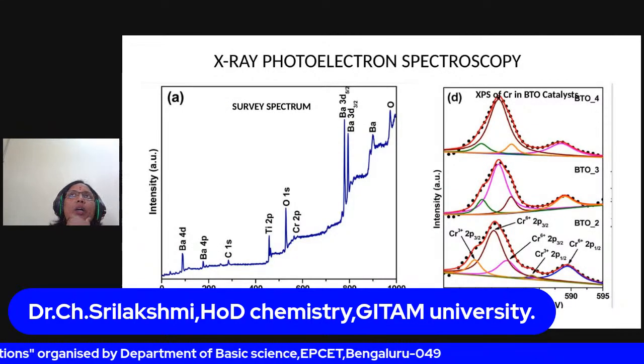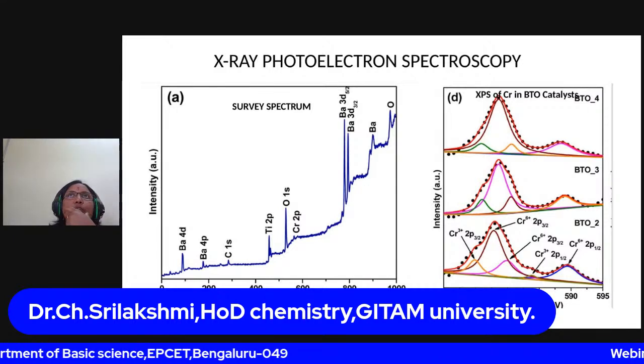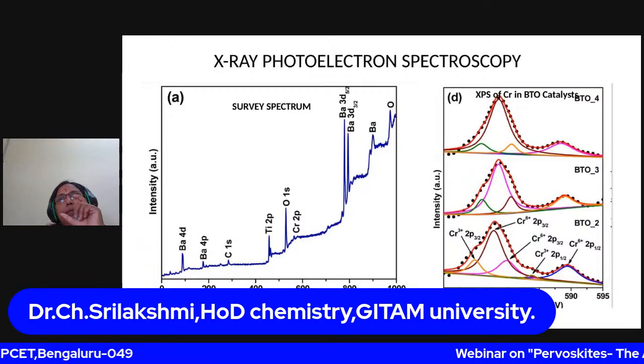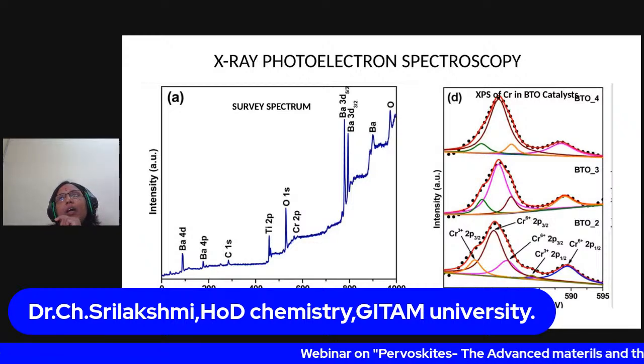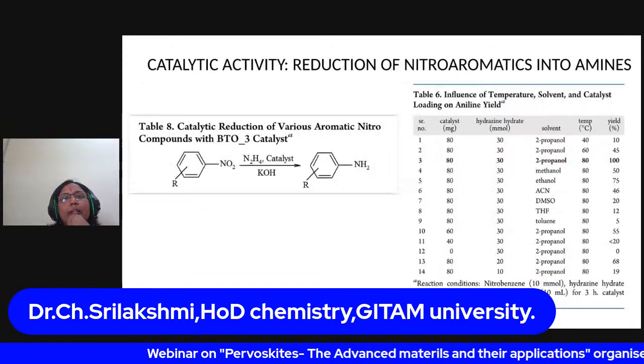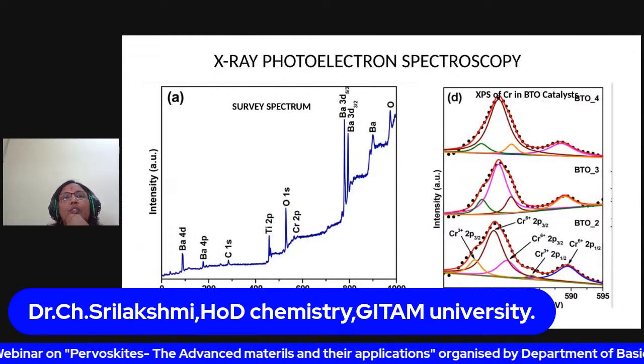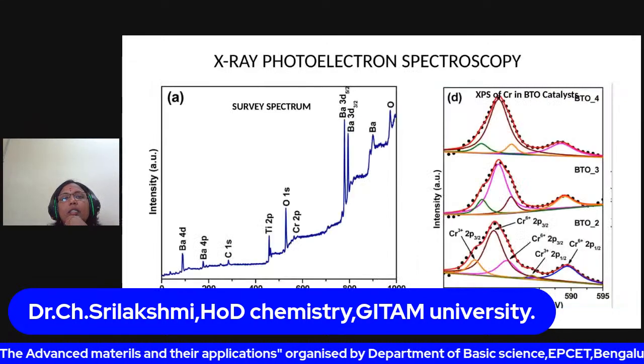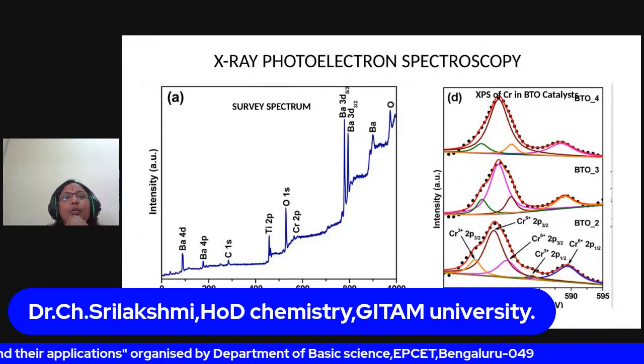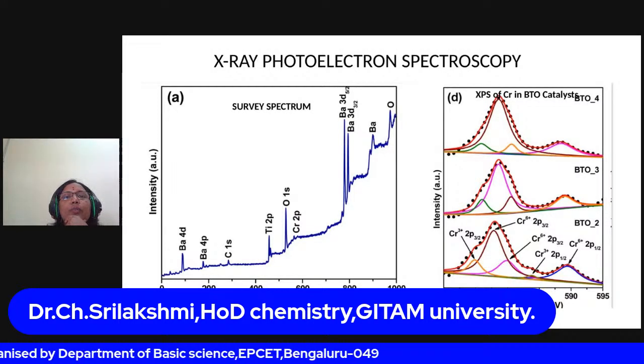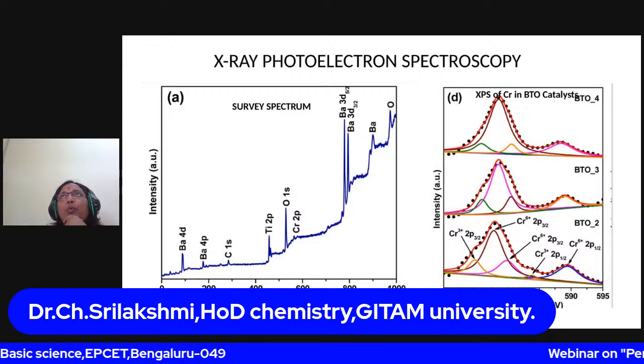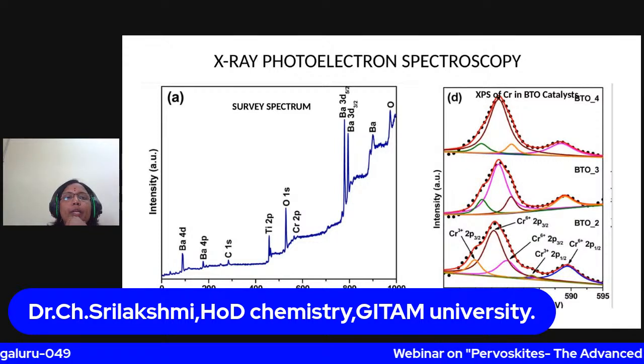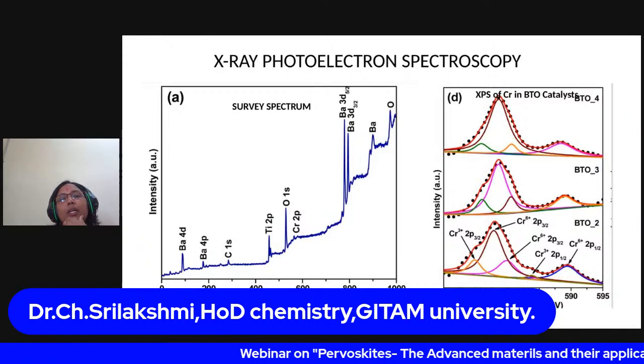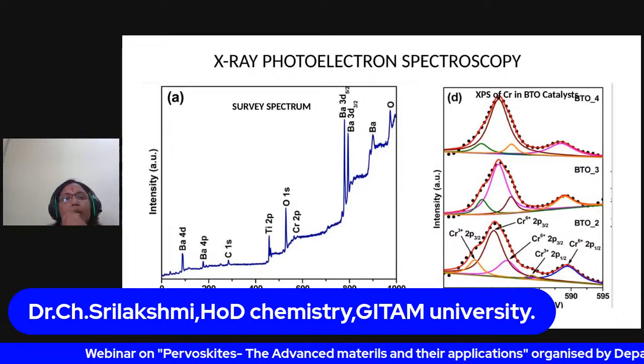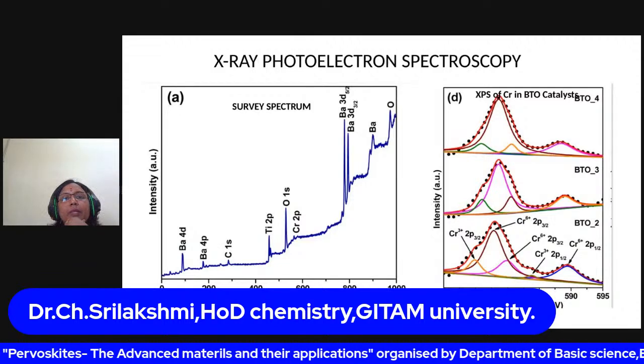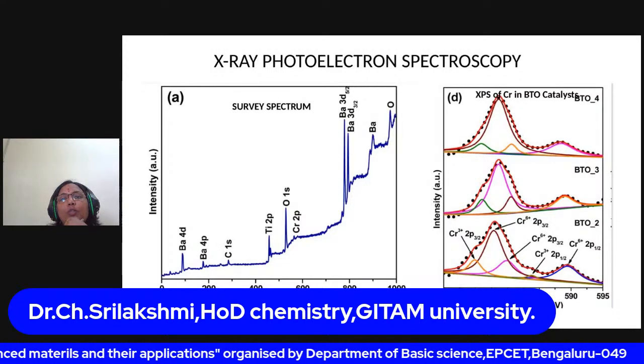So XPS. Why should we use XPS? One is elemental composition, another is the chemical state of the sample. So this is the survey spectrum, where you can see the presence of all the elements that the sample is composed of. For example, carbon is not in the sample, so where does this carbon come from? Maybe it is picked up from the atmosphere. Apart from that, barium, titanium, chromium, and oxygen are there.